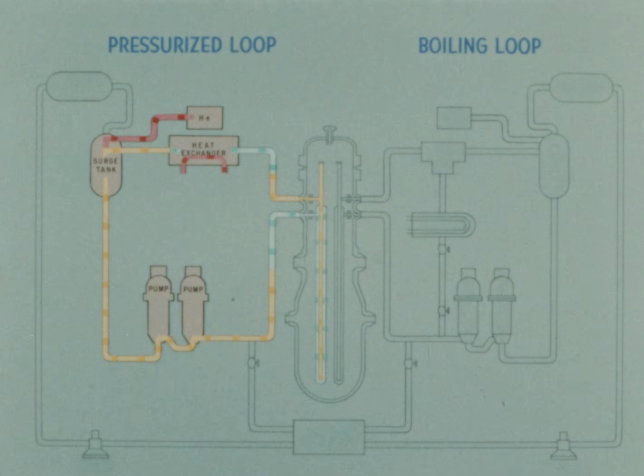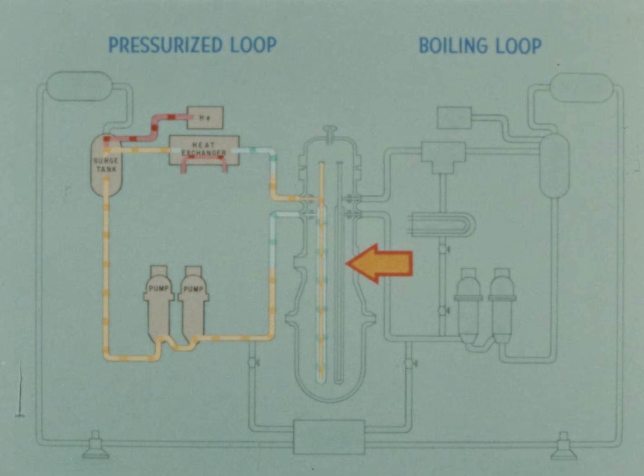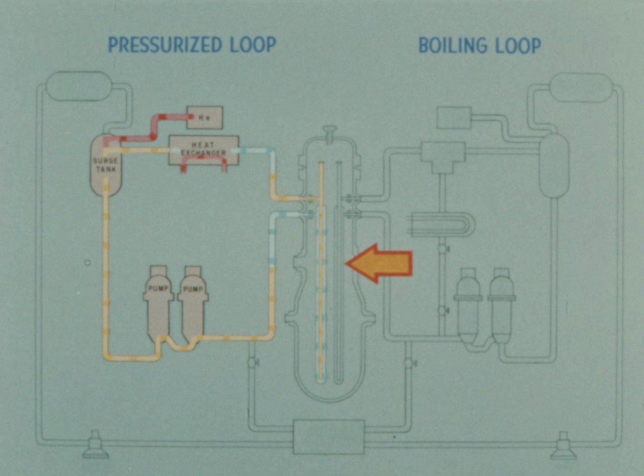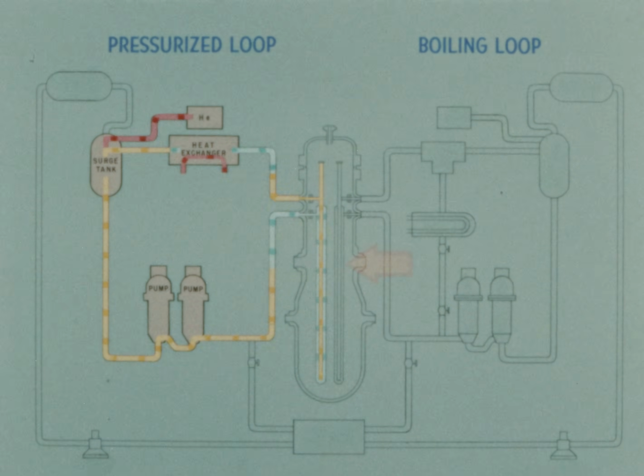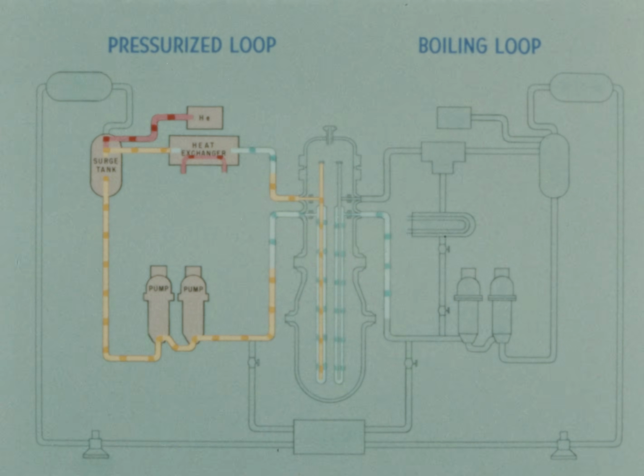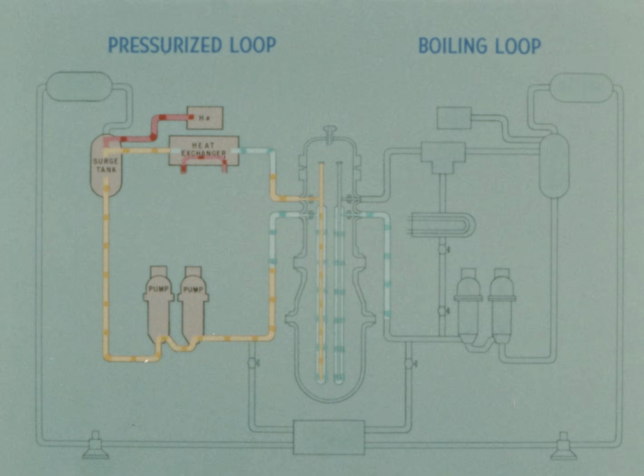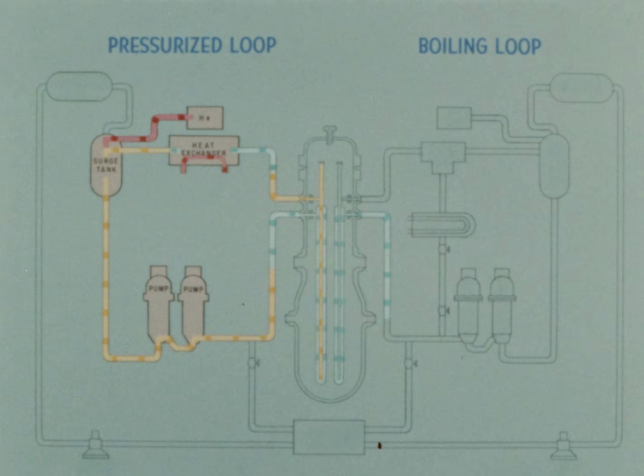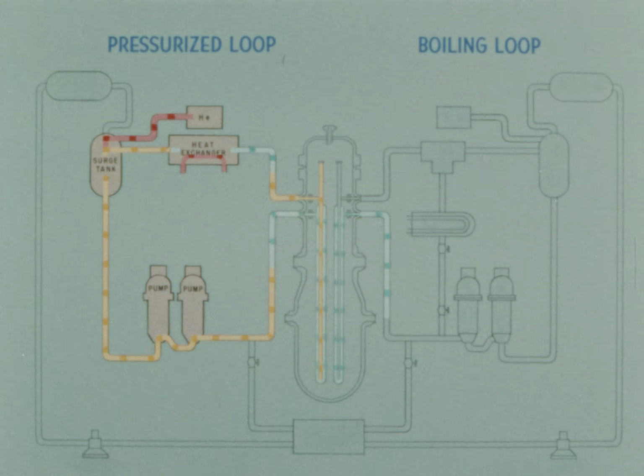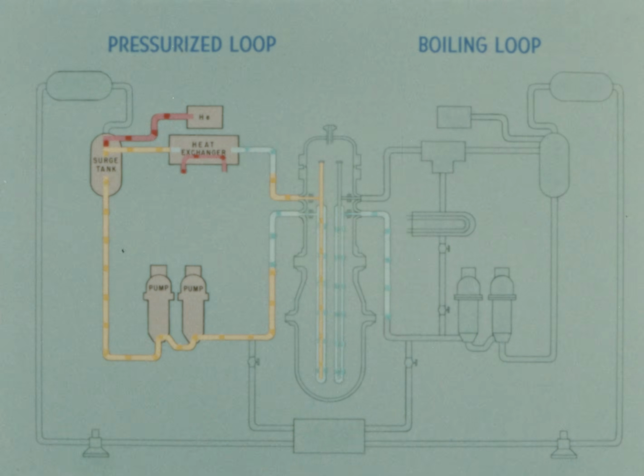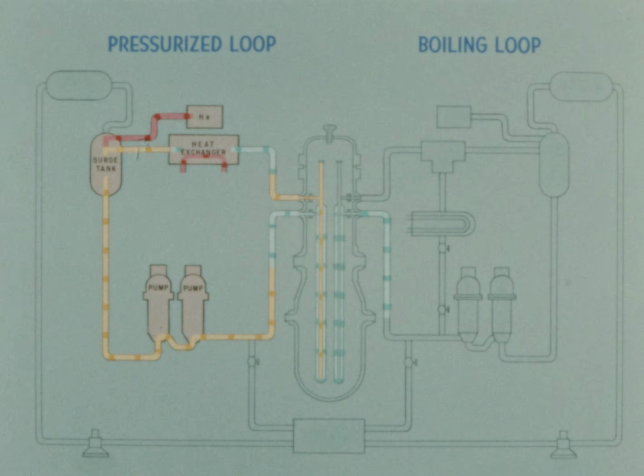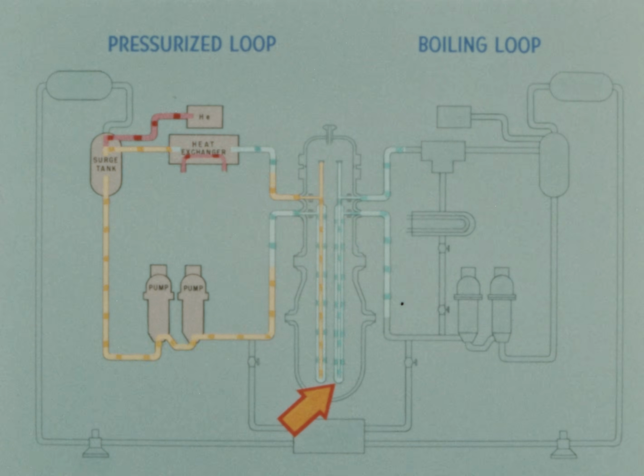The other installed loop will permit tests at boiling reactor conditions. The loop tube for the boiling loop is almost identical to that of the pressurized water loop. The cooling conditions of this loop can be adjusted to provide operating conditions over a range of interest to boiling D2O reactors. Steam qualities from 10 to 30% can be obtained at the outlet of the loop tube.